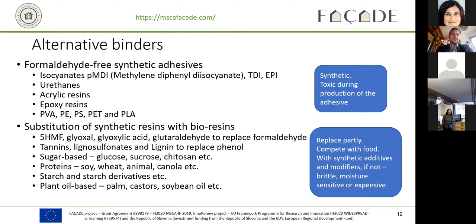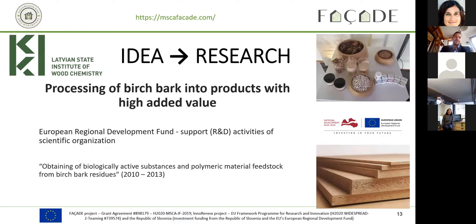But still, there are some problems with the bio-based adhesives because they replace only partly, and synthetic additives and modifiers must be added to improve mechanical properties and moisture resistance in some cases. They compete with food. And there is another alternative, suberinic acid binder, which is a natural, biological, and innovative material obtained from birch outer bark. And now I will speak about how we started our research. We started with the idea of processing of birch bark products with high added values to solve these problems I mentioned before.